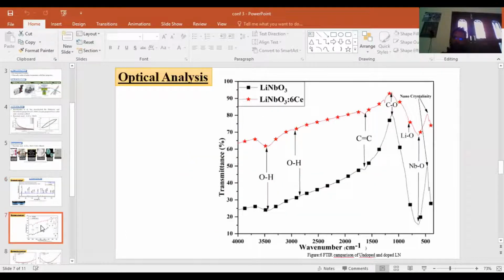I also used FTIR characterization to get the functional group and bonding, and it is clearly shown that lithium oxide bonding and niobium oxide bonding is present in my material. I used potassium bromide for pellet making for the FTIR characterization.